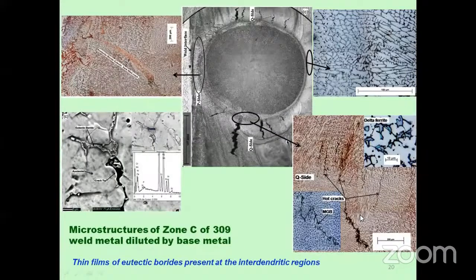So when we did the detailed microstructural analysis of this specimen, this is the tested specimen. We see these cracks here at a certain region away from the weld interface. So whether cracking has happened near to the weld interface where this base metal dilution is more, yes, this is the microstructure, taken very near to the weld interface. It is not that cracking has not occurred. This shows that cracking has occurred, but it is getting backfilled by the eutectic near the weld interface because it is very close to the base metal.